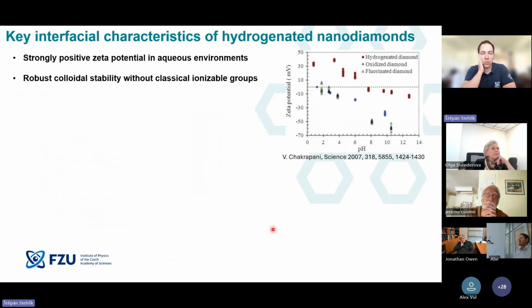But when we turned to the hydrogenated nanodiamonds, we suddenly see exactly the opposite thing. We see a strongly positive zeta potential in aqueous environments. It has been demonstrated, I believe for the first time in 2007, for hydrogenated diamond powder. But since then it was reported many times, and I think it's widely known that hydrogenated nanodiamonds have quite robust colloidal stability, but still without these classical ionizable groups.